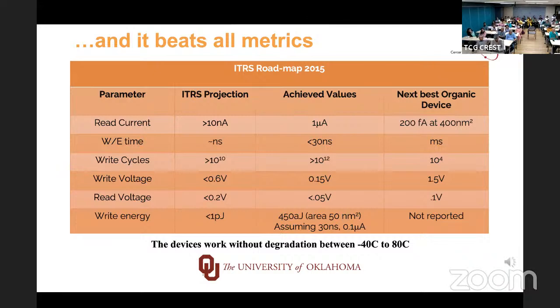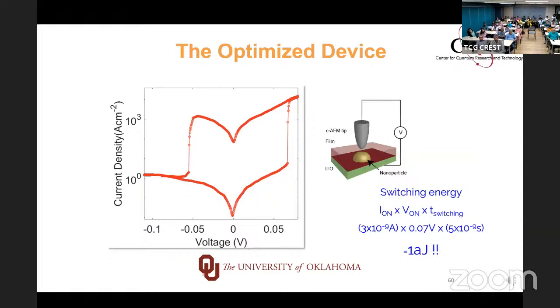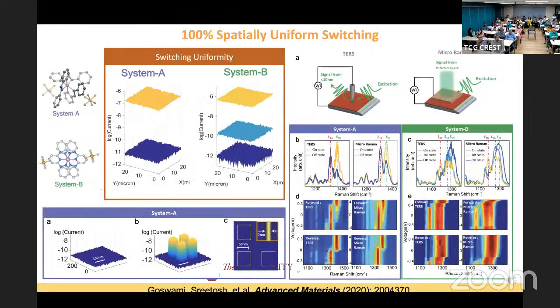In fact, one of the exciting devices, where now we are down to about 70 millivolts switching voltage, and the switching energy is about 1 attojoule, basically. And this assumes the switching time of 5 nanoseconds, which is the one that we measured, but our measurement is still limited by our measurement apparatus. I think this device will probably switch at about 0.5 nanosecond, and it's probably more like 100 zeptojoules for the switching energy of this device. So this is really ultra low energy switching, and it's spatially uniform.